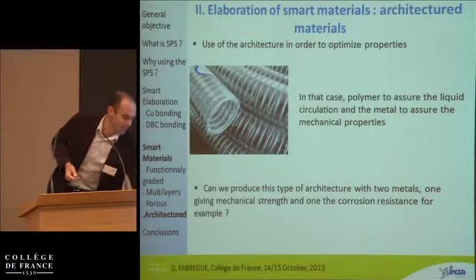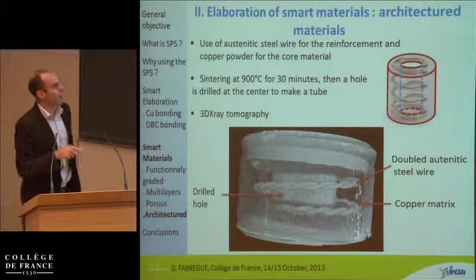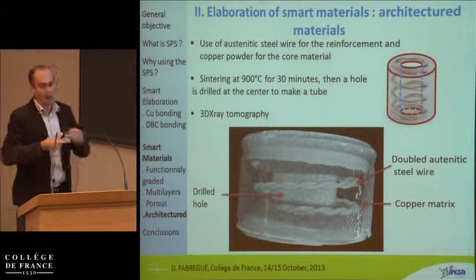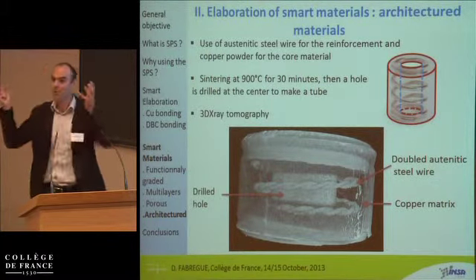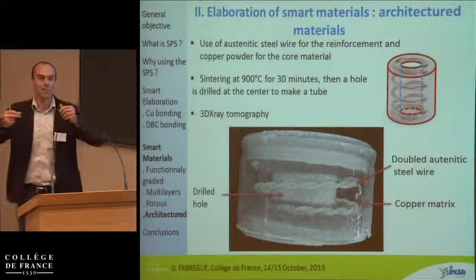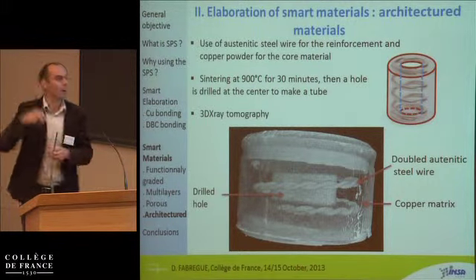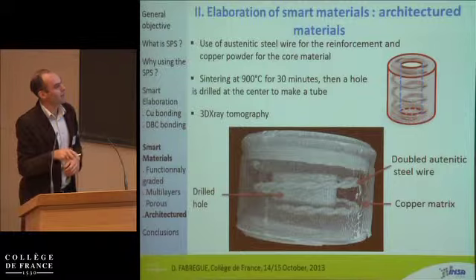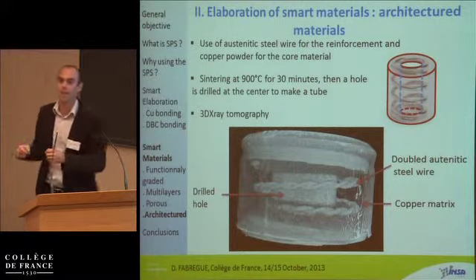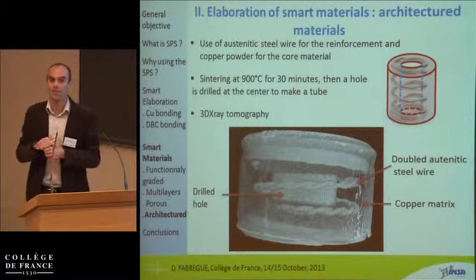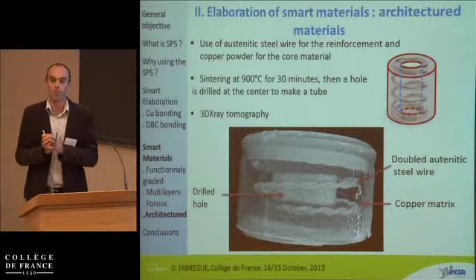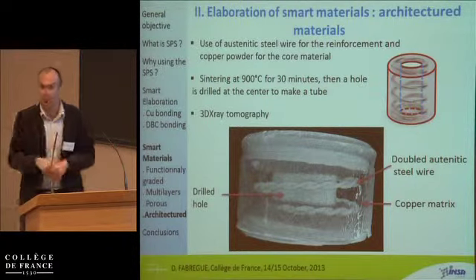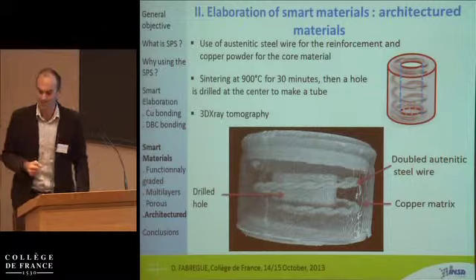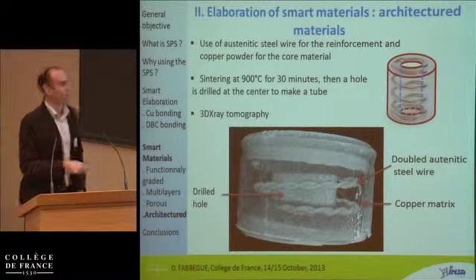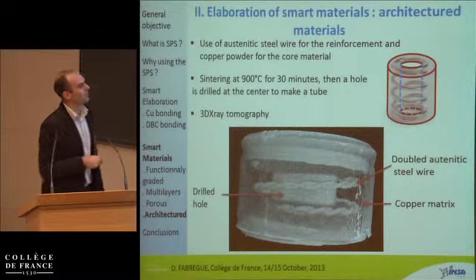So the idea is pretty simple. We took a steel wire. I doubled that, so I will use my hand also. I double the steel wire, make a helicoid here, and then I put that in the mold, putting copper powder inside, and I sinter the two of them. And then I can drill a hole. I wanted a hole to make exactly the same thing as the picture, but you don't have to drill the hole if you don't want.